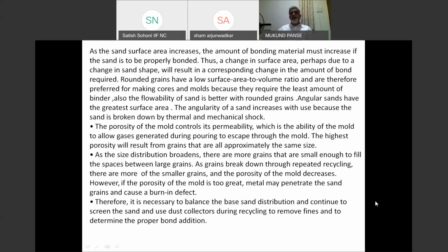If you don't have rounded grains, the sand surface increases and the bonding material required increases. The rounded grains also have better flowability, better permeability. The porosity of the mold controls the permeability. When the grains are compacted, rounded grains will leave certain voids, provided you have proper distribution of sand. You try and procure sand with a 3 or 4 sieve distribution, it is 80%, so that there are not many fines and the gap between the two grains is not filled by the fines. You get good permeability.